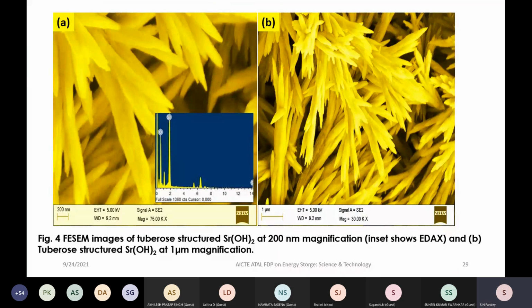FESEM structure, then it is very beautiful, that tuberose structure is here. If you see it carefully, one can see that due to this tuberose structure, the surface area is going to increase. And one can see here the inset, the EDX. In the EDX we are having the different components: strontium is present here, oxygen is present here, and there will be some peak due to the carbon. So if you are doing the experiment in open air, then the carbon peak is also present there.